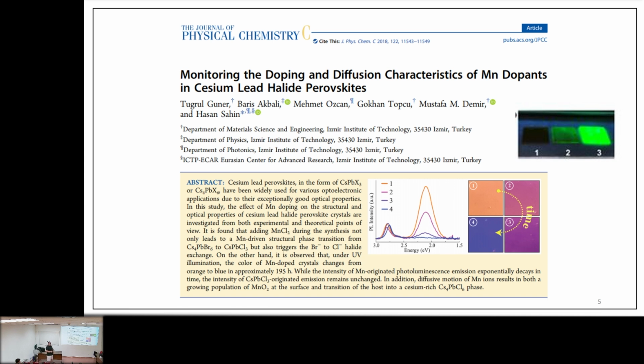For example, here an electronic structure calculation. So if you perform electronic structure calculation, so I have cesium lead bromide, and together with manganese atoms, I calculated the energy band diagram. And then if you remove manganese atoms, you will have no mid-gap states in your energy band diagram.